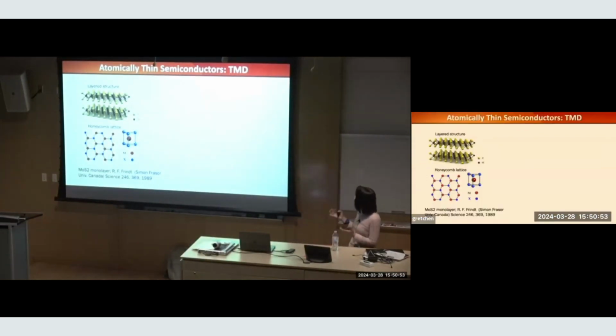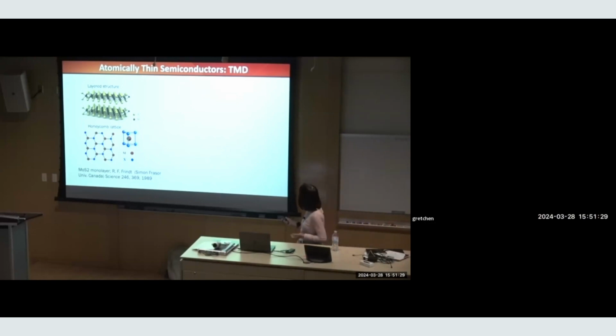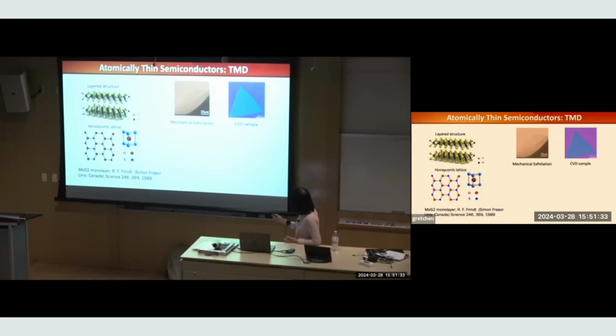The main material I'm going to focus on today is the semiconductors. They have 3 atomic layers with a transition metal in the middle and chalcogen atoms on both sides. If you look at this material top down, you see a honeycomb lattice with the A and B sites occupied by different atoms. And this MoS2 monolayer indeed was created, isolated quite some time ago by scientists in Canada and published in a decent journal. But at that time, people were not studying their optical property, which is what I'm going to talk about today. So you can create them using the exfoliation method coming from a bulk crystal, thin them down to monolayer, bilayer, whatever thickness you want to create.